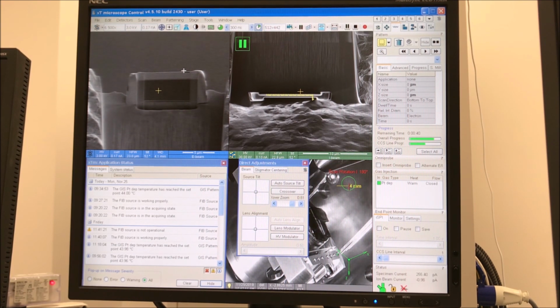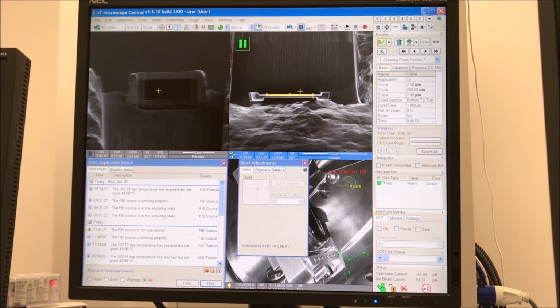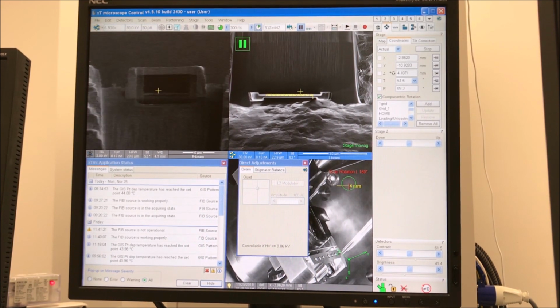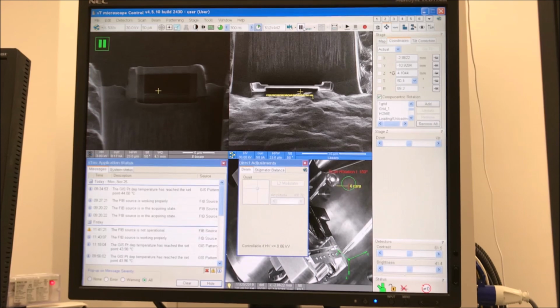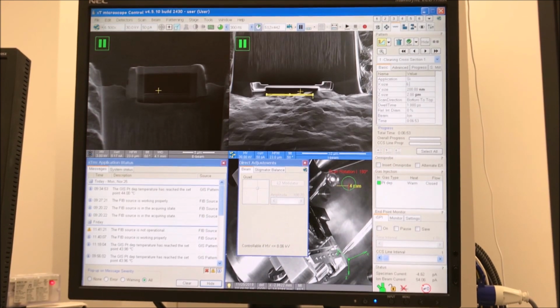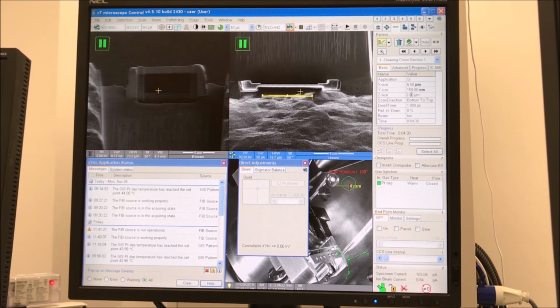And once this pattern is done, I'm going to tilt minus 1 degree from normal incidence, drop my beam current down again, this time to 50 picoamps, and once again, I'm going to rotate the cleaning cross-section now to 0 degrees. I'm going to bring the X dimension in a little bit to again stagger the cuts and execute this pattern from the bottom of the lamella.